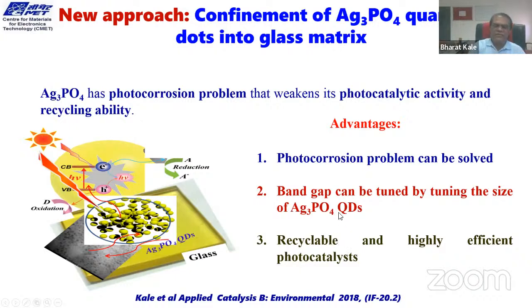So considering that, we thought whether these Ag3PO4 nanoparticles can be grown in the phosphate glass and see their stability. And exactly, we found that the Ag3PO4 is highly stable in the glass. If you see the structure of Ag3PO4, we can observe highly intense dodecahedrons, and similar very small tiny dodecahedrons are also observed in the glass.